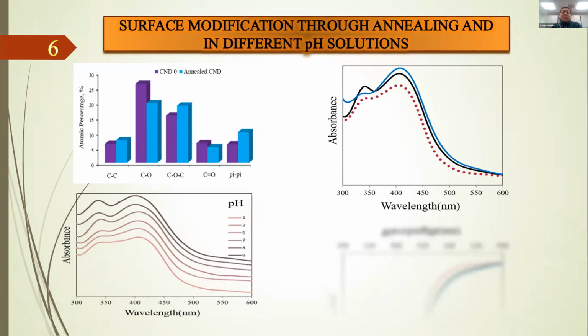We removed C=O from the surface of the carbon nanodots by annealing, and in acidic solution, the double bond character of the C=O in COOH is also decreased. Comparing this to the absorption spectrum, we can reinforce the fact that the C=O emission affects the 340 nanometer peak, as they both look very similar.